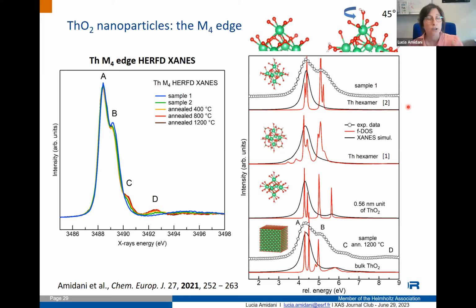And then to go back to my L3 edge studies, where my hypothesis was 2.5 nanometer nanoparticles, I think that simulations taking into account the presence of this small cluster would already bring us much closer to the result and to the disappearance of this feature A. Actually, I think we could even get the result by just considering no relaxation of the surface, but just the presence of those clusters.